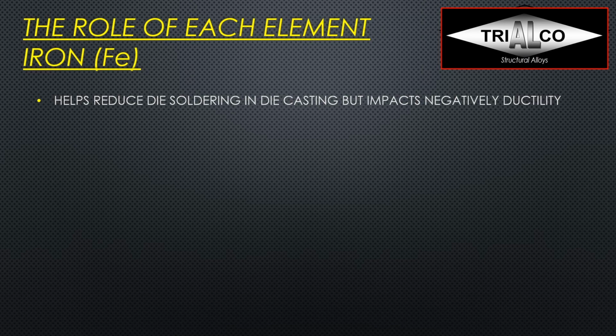So now let's talk about iron, and there are actually aluminum iron alloys that use it as an alloying element. You pretty quickly get to the eutectic point. I think it's around 1.6%. But really in most other alloys, and pretty much all other alloys, it is just an impurity and has to be limited. But it helps reduce die soldering in die casting. That's where you can find most of the iron. So most die casting alloys will be at 1 to even up to 1.3% iron. But we know it impacts ductility negatively.